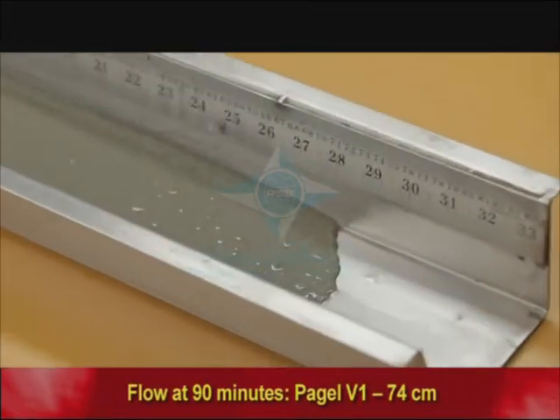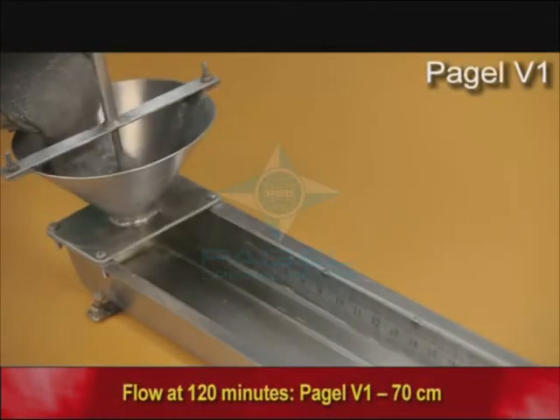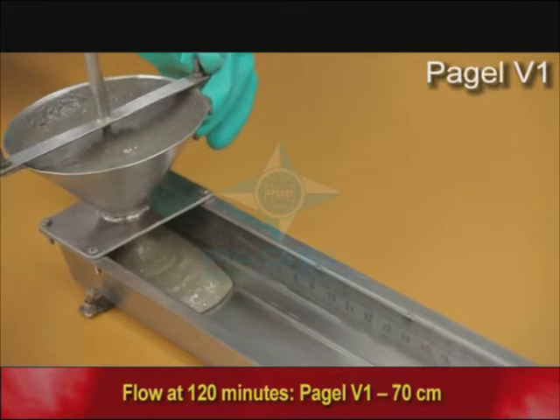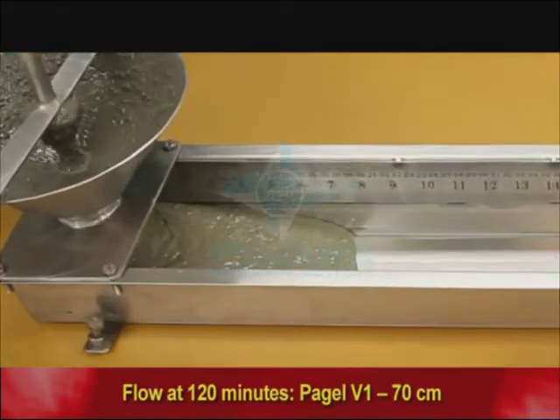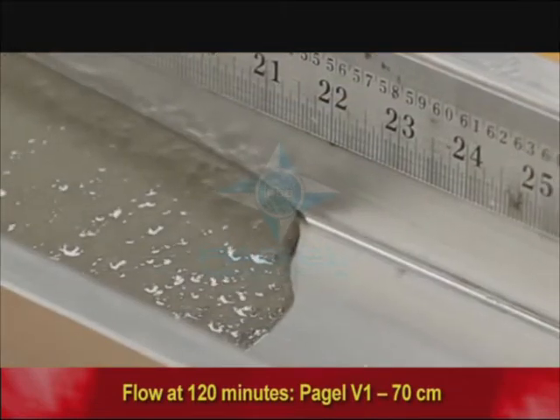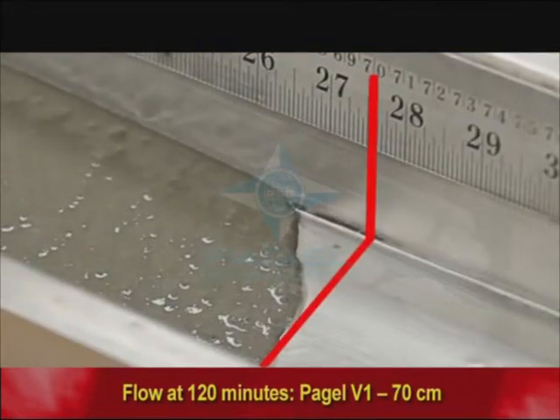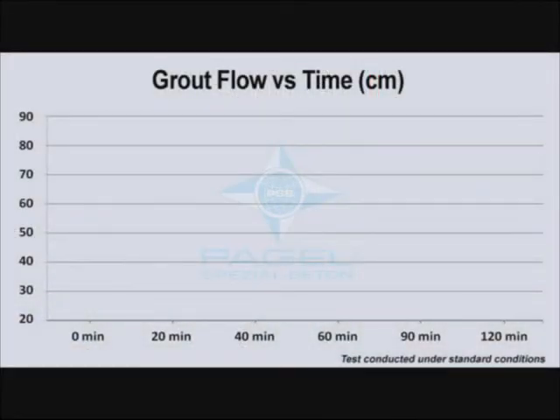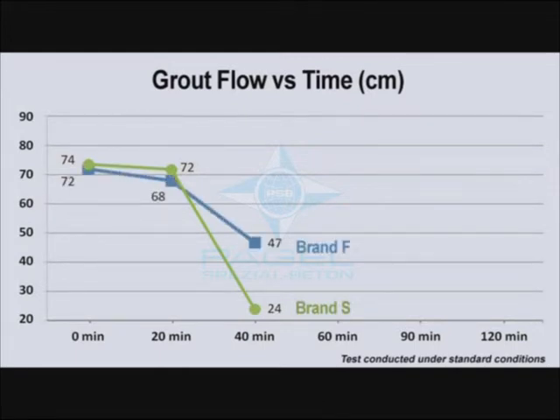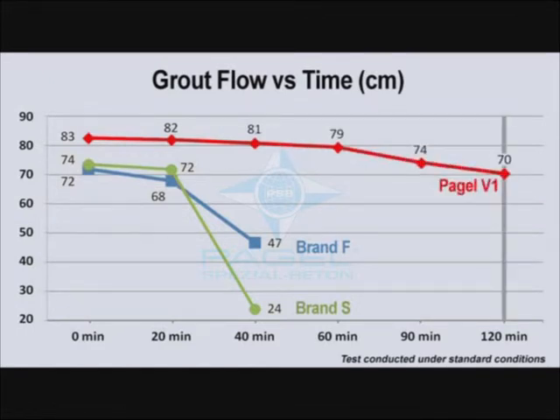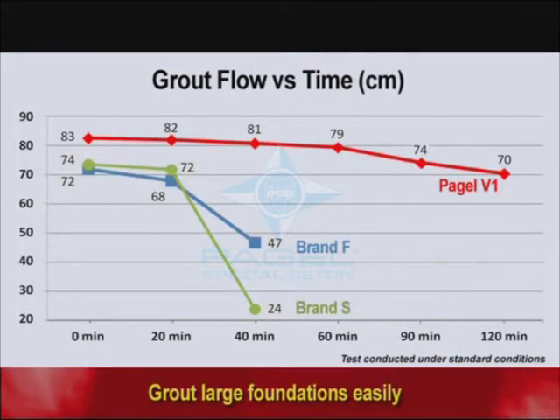After 90 minutes, the Pagel V1 grout still flows 74 centimeters. And amazingly, after a full 120 minutes, the Pagel V1 grout is still almost unaffected and flows an unbelievable 70 centimeters. Therefore, against an effective pot life of not even 40 minutes for brand S and brand F, the Pagel V1 grout has a pot life of over 120 minutes with negligible loss of flowability. This allows you to grout large foundations easily without having to worry about loss of flow with time.